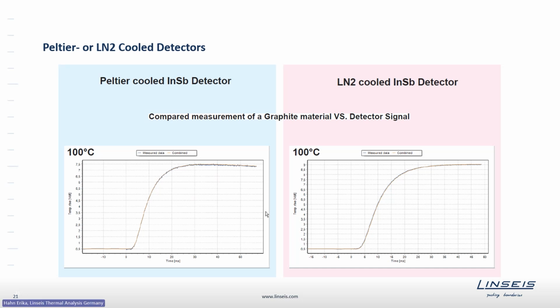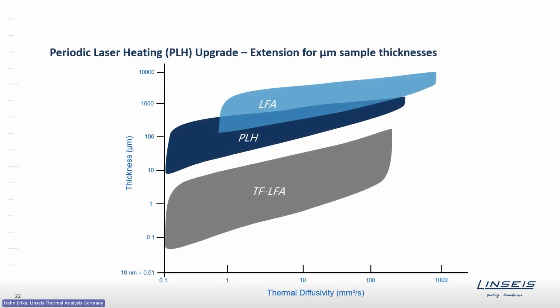As a further option with which the system can be equipped, I have mentioned the PLH option, and I want to briefly explain it to you right now. As I have told you, the laser flash is a system designed for the thermal diffusivity measurement of solid materials in the range of 0.1 to 6 millimeter. Even the 0.1 millimeter sometimes cannot be realized that well. The issue here is that the response of the sample is very fast and might be too fast for the length of the pulse. So the length of the pulse should not overlap with the reaction of the sample, and for very thin samples, this might happen.